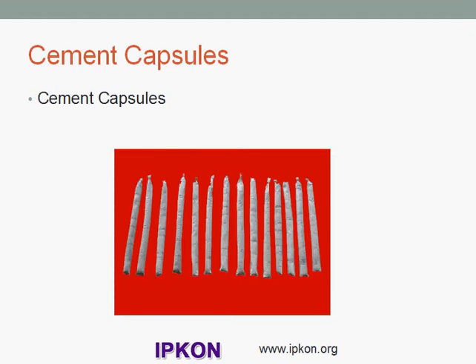IPKON perceived the following limitations in the existing capsules. First of all, cement capsules. Cement capsules have a short shelf life of 6 months because the shell of the capsules is made with a water permeable material. During their storage, the capsule is affected by any humidity in the ambient air. They need to be soaked in water before being installed.